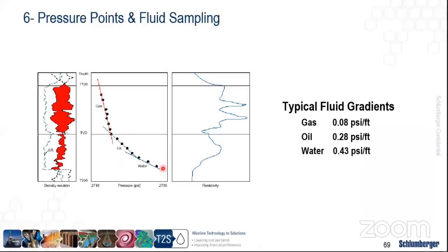By getting different pressure points at different depths, so this is depth versus pressure, we can get the trend lines of the different fluids that we have, such as water, oil, or gas. By intersecting the trend lines together, we can get the contacts of each fluid, for example the gas-oil contact or the oil-water contact. So these are typical values for the gradients that we have for gas, oil, and water.